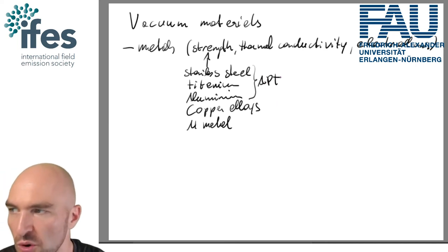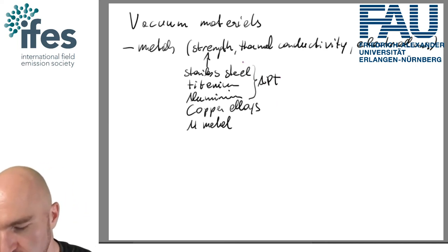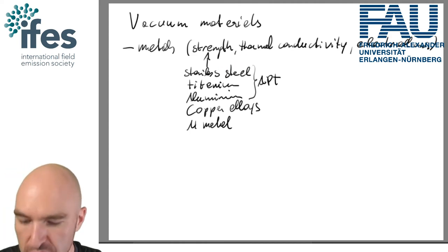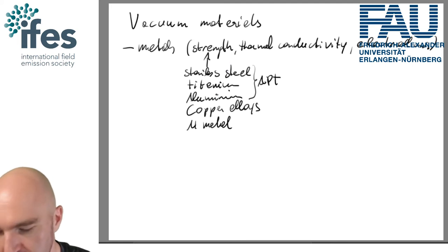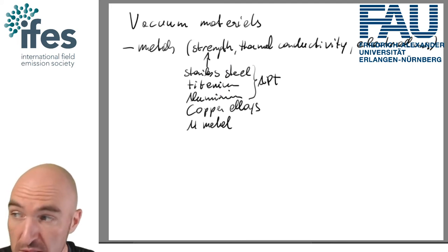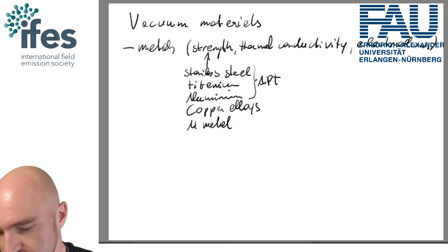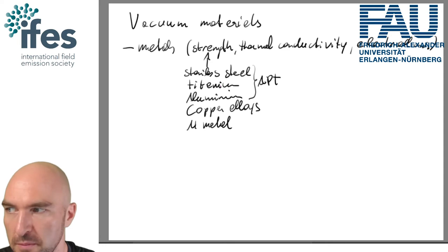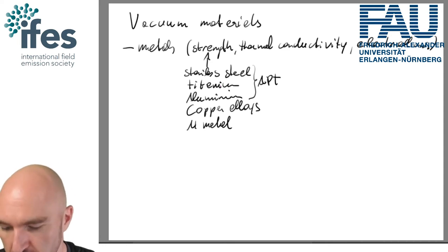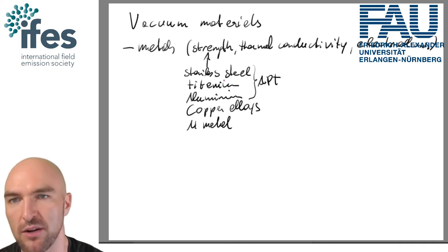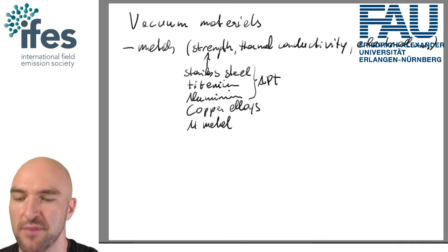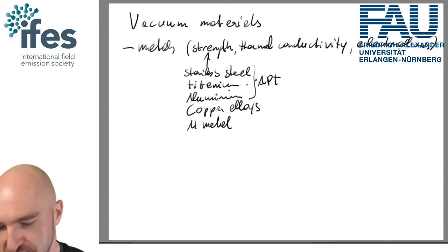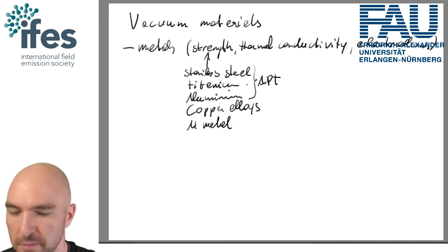I'm not going to go through the outgassing properties of the different materials, but essentially stainless steel has a downside of hydrogen outgassing. Aluminium has the downside of non-specific outgassing, not hydrogen outgassing. So it might be better for atom probe tomography than stainless steel. But the problem is, and you'll see that later with flanges, it's easy to damage as well. Titanium has no hydrogen outgassing and also relatively low levels of other contaminants. So this is pretty much the deluxe material for making an atom probe.